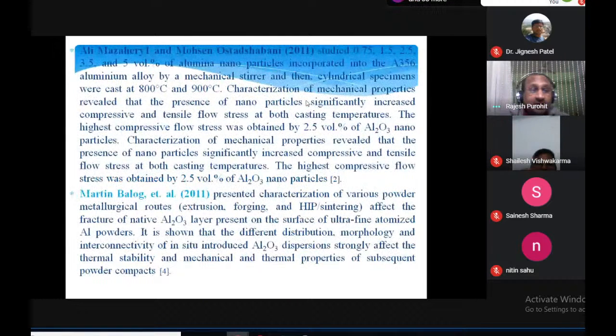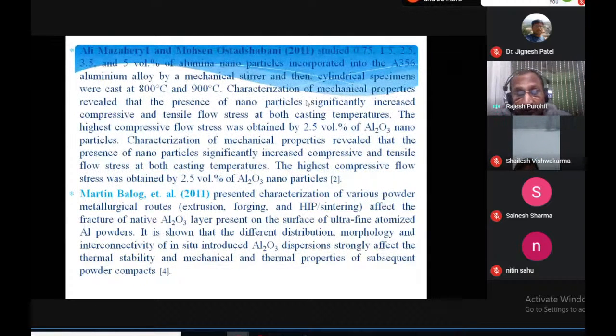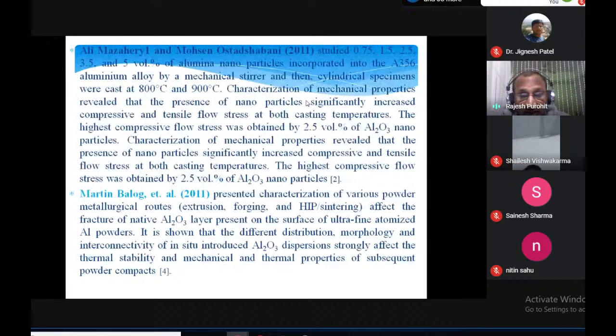Similarly, another author, Ali Mazaheri and Mohsen Ostadshabani, studied different volume percent of the alumina nanoparticle incorporated into the A356 aluminum alloy by a mechanical stir, and then a cylindrical specimen were cast at 800. So this paper is quite more related to our work. So stir casting is used. Same process we have also used in our research finding. So we have cast at about 800 and 900 degrees centigrade.